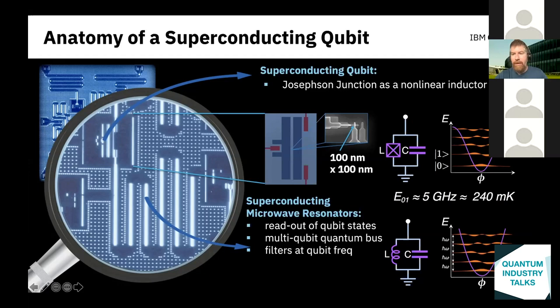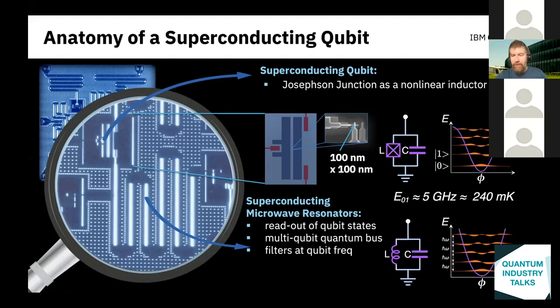This energy level is variable due to the fact that the aluminum oxide is glassy and grown, so even under the same growth conditions it will be different for each junction. We use fixed frequency transmons, which are difficult to change after fabrication. These typically come out to an energy around five gigahertz, and that energy multiplied by h-bar and divided by Boltzmann's constant corresponds to about 240 millikelvin. This is the reason why we have to operate these superconducting qubits at temperatures way colder than the critical temperatures of one and nine Kelvin — much less than 240 millikelvin.